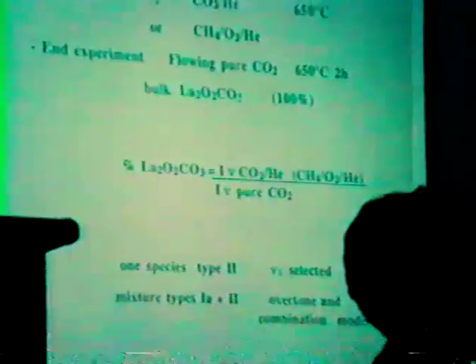So the percentage of the oxycarbonate was determined from the integrated intensity of a selected mode after the O2 helium or the catalytic mixture and after pure CO2 treatments. And you have seen that at the end of the experiment you have only one species which corresponds to the hexagonal polymorph. And so we have chosen this one, which is fundamental.